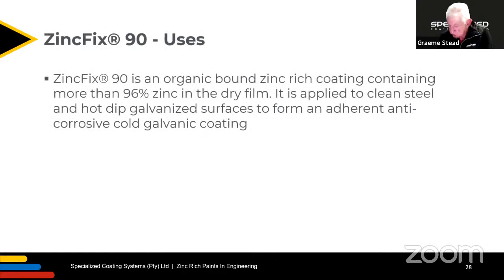Okay, then we go on to ZincFix 90, organic bound zinc rich film, 96% zinc in the dry film. And this is where I said you have to agitate the zinc while applying it, especially by spray, because if you use roller or brush, it's being agitated by the implements.